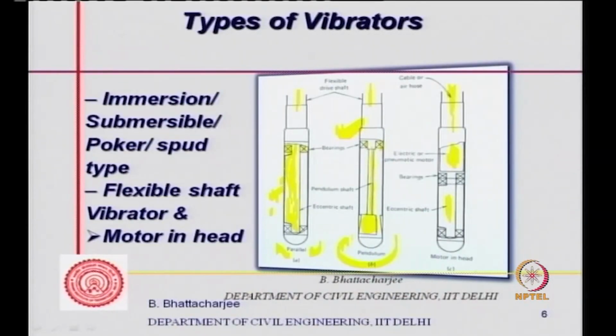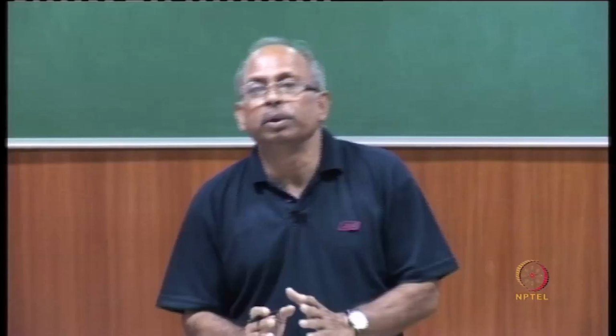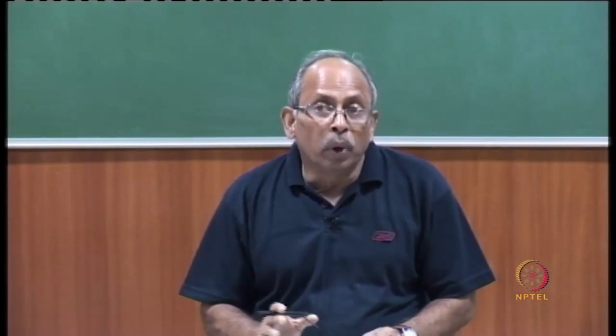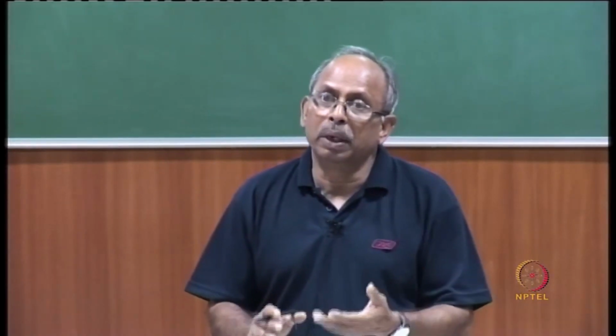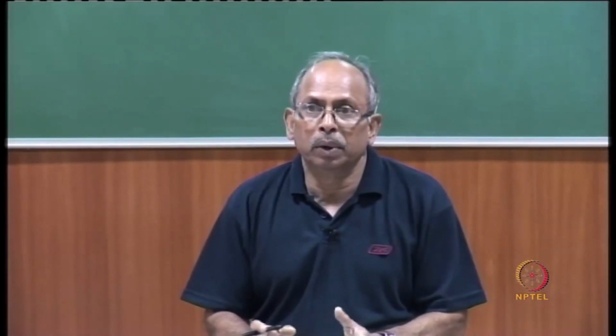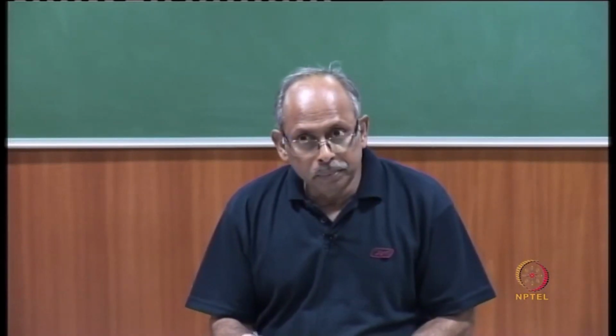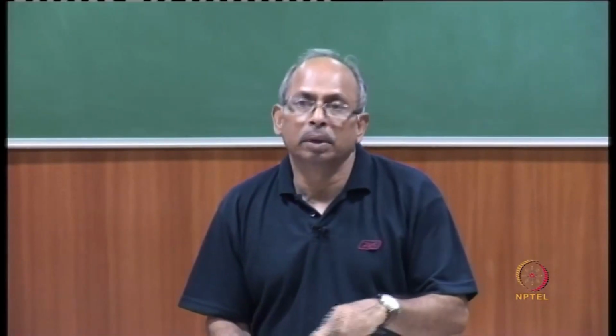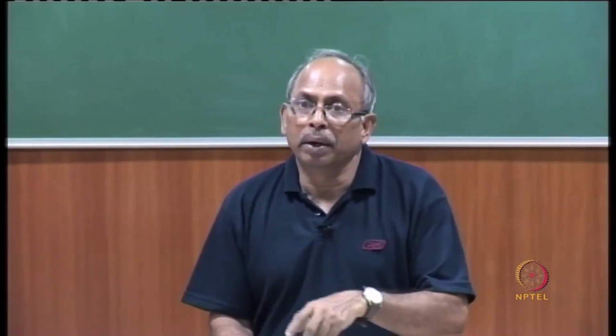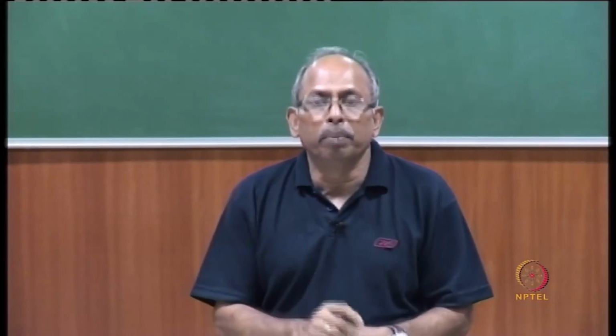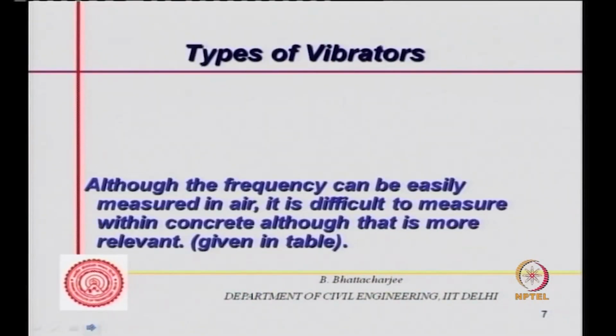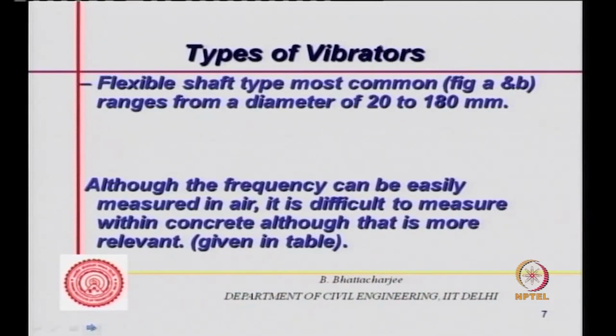Actually, the needle vibrator, as we call it. This component of the equipment goes inside the concrete and causes oscillatory motion in the concrete around it, which will be compressed and rarefied, and so on and so forth, radially going outward. Largely it will be generating longitudinal waves, and maybe some transverse waves too, but it causes oscillatory motion that spreads around over a circular area having a radius of influence. So what you do is shift from one place to the other, and go on vibrating the concrete.